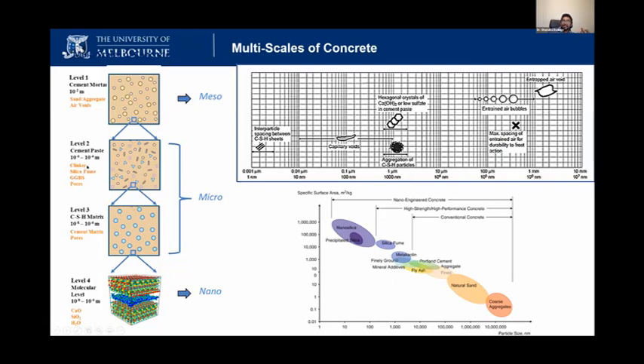Then we can still see the unreacted cement in very high strength concrete, because in very high strength concrete, due to the very low water to binder ratio, the cement doesn't fully react because it doesn't have enough water. So some of the cement reacts and forms the C-S-H gel, calcium silicate hydrate gel. Then we can see the unreacted silica fume, the fly ash, and the pores. We can see the pores, and also silica fume as well.